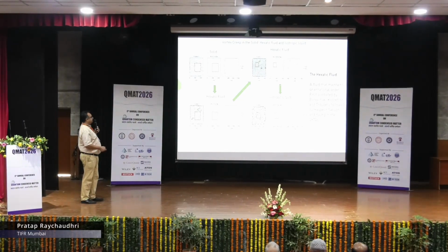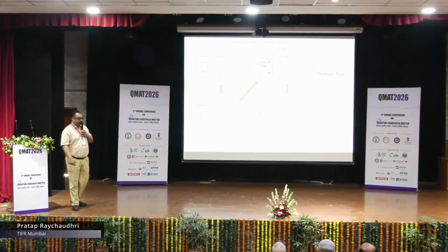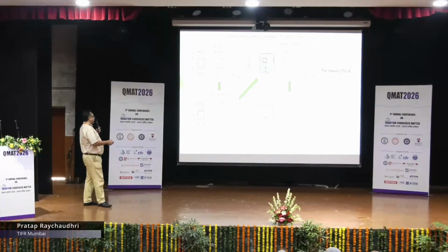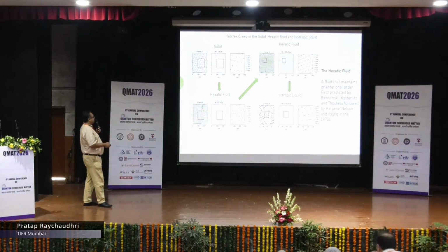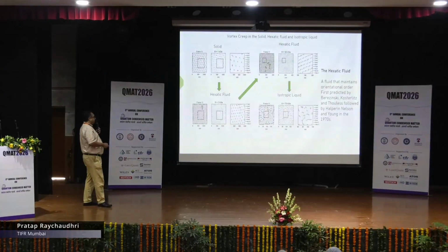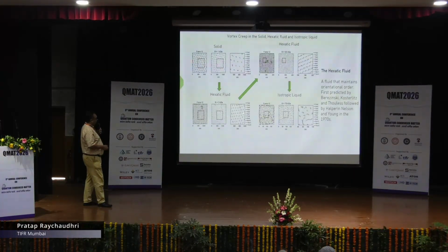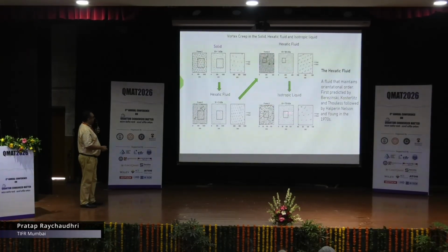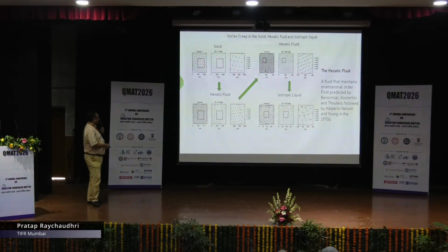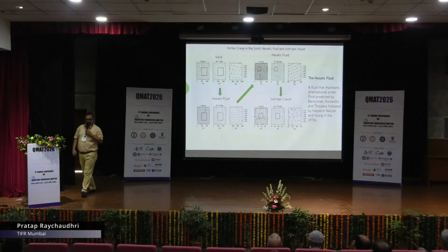At very high field, like 70 kilogauss, now the vortex motion is completely random, and that is what we have studied as Brownian motion in school. However, in between, you have this state where the vortices have considerable motion, but if you see carefully over the long time scale, the motions are very directional. So they are moving, but not randomly as you can see here, but they are moving along the principal axis of the underlying hexagonal lattice.